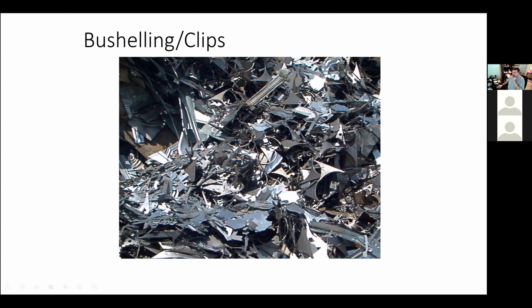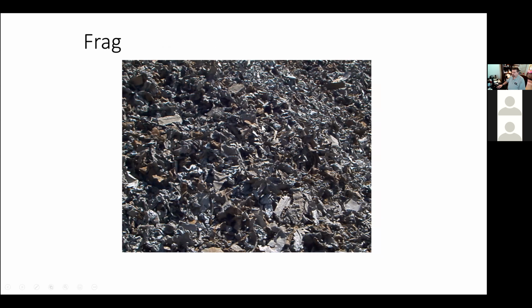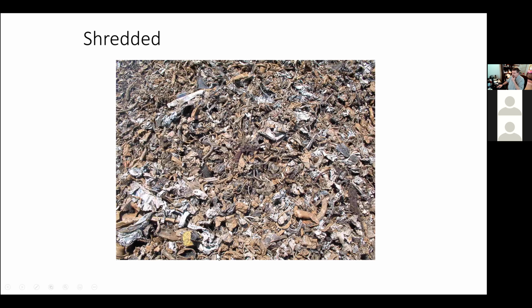So some of the different types of scrap, we have some scrap types which we call prompt scrap. So this is busheling and clips. This is scrap that's generated from recent processing. So basically we take sheets of steel, they go into a manufacturing process, they stamp out parts, and what's left over is called busheling and clips. Frag is basically material that's being shredded, but it tends to be heavier, more dense than your typical shredded scrap. This is shredded scrap here. And we used to refer to this as shredded automotive. Now people are shredding a lot of other grades of scrap as well, which is causing a bit of a problem, because typically shredded automotive scrap, you could get it with as low as a 0.12 weight percent copper content. Now it's trending up closer to 0.3, 0.35.